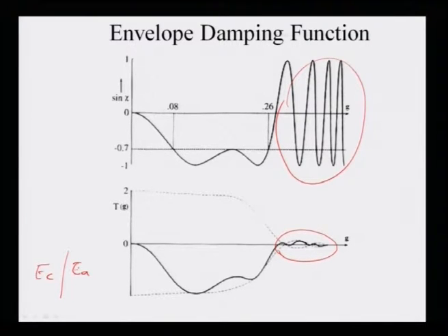Whatever may be the situation, as you can clearly see, there are all these zeros at higher values than G1, but beyond that the values of the transfer function T(g) are very small, and whether this can actually affect the resolution or the information in the microscope needs to be analyzed, and it has been seen that it can. Therefore, although the resolution limit will be given by the first crossover, the information limit can be higher. The information limit can be given by this point G2, which is at a higher spatial frequency.